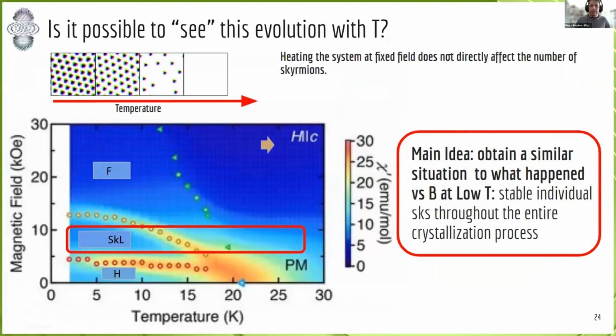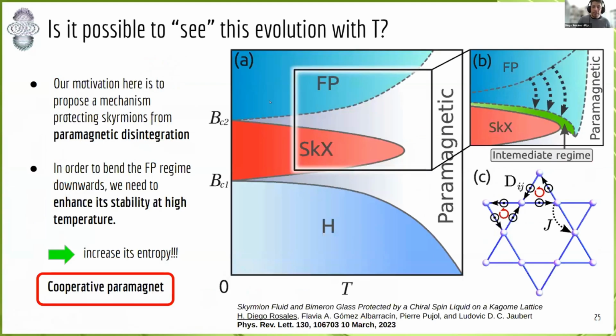The question we have in mind is to try to induce this sequence of different skyrmion phases, but now as a function of temperature. You can see that this situation is possible at low field, where the entropy of the system is very small, at very low temperature. But here, the presence of strong thermal fluctuation makes it difficult for the ordered state to compete with the paramagnetic state. Then our motivation to solve this problem is to try to move this part of the phase diagram, the fully polarized regime, to this part. But to do this, we need to increase the entropy of this ferromagnetic state.